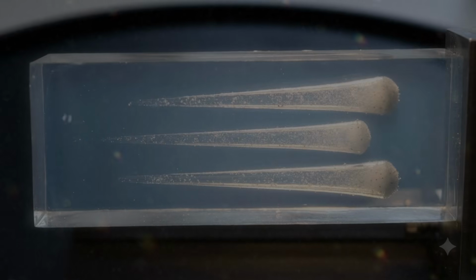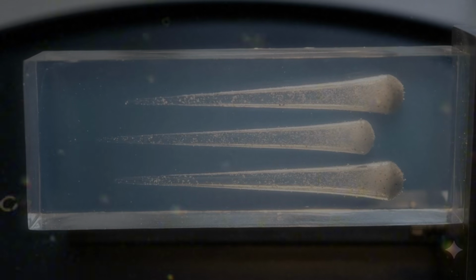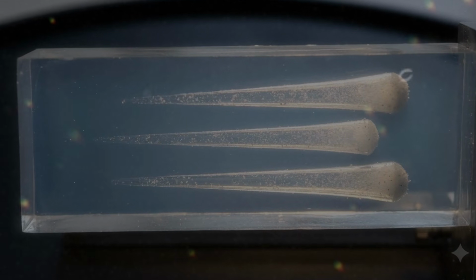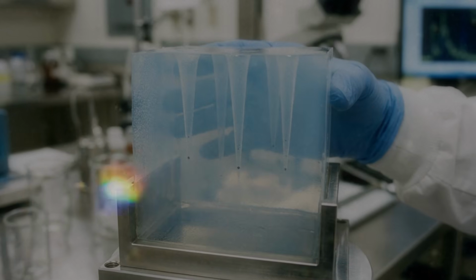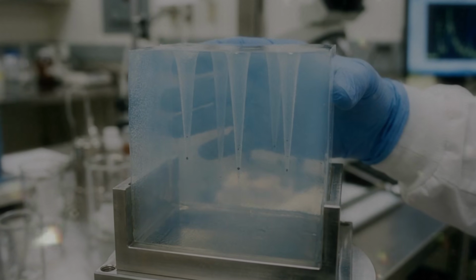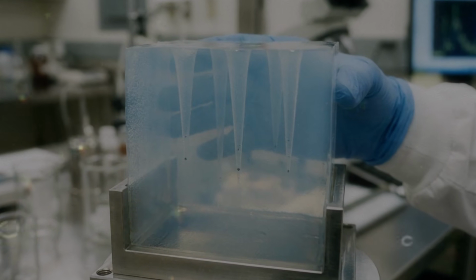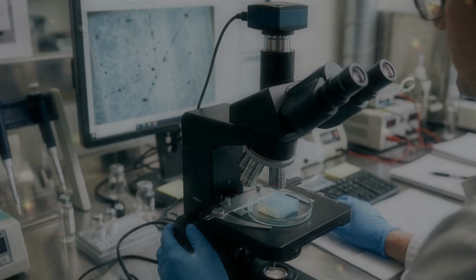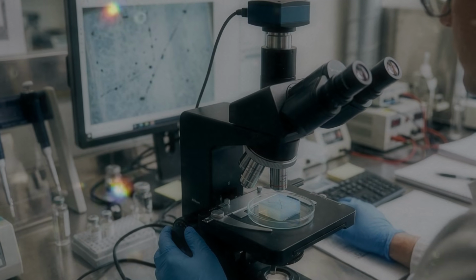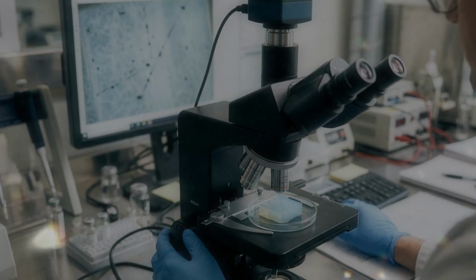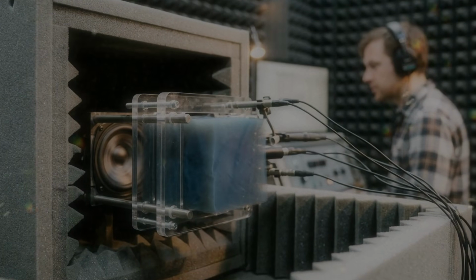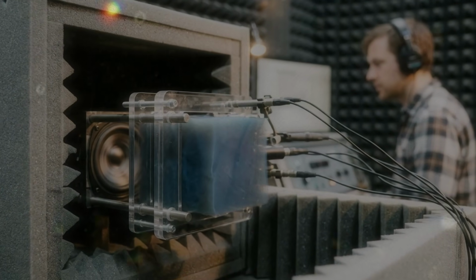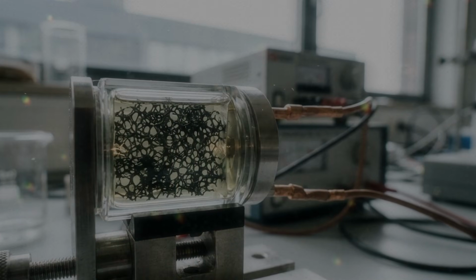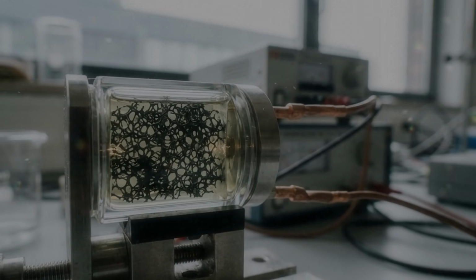The same lightness that makes the dry sample impressive creates a demanding test once it is full. A material that weighs almost nothing may be asked to hold a quantity of liquid hundreds of times greater than its dry mass. Strong connections between sheets become essential. Electrical conduction must survive the same movements. A graphene aerogel may remain conductive while it is compressed, although its resistance usually changes. This allows it to function as both a mechanical structure and an electrical component.